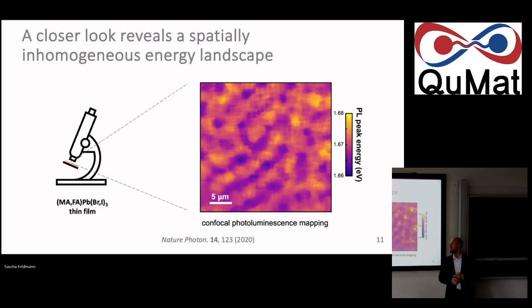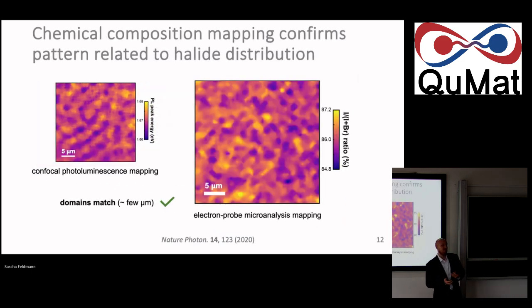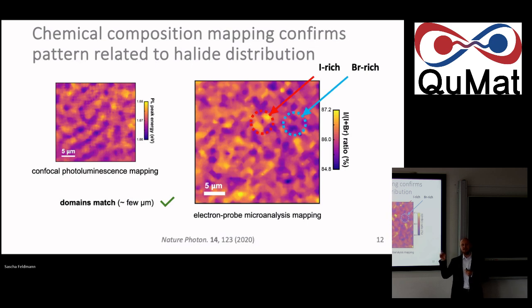Again, very heterogeneous. If we then ask where that comes from, and we correlate and overlay this with the chemical composition of the film, which we can do with a technique called electron probe microanalysis, basically a nice element-specific X-ray fluorescence, you will see that it's the local ratio of iodide to bromide building blocks in this mixed film that is varied, locally higher or lower. You have locally more iodide or bromide, and this modulates the optical band gap that we saw in the map here. So this is where it comes from.